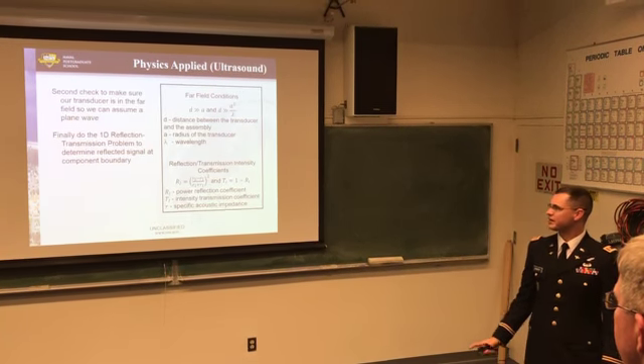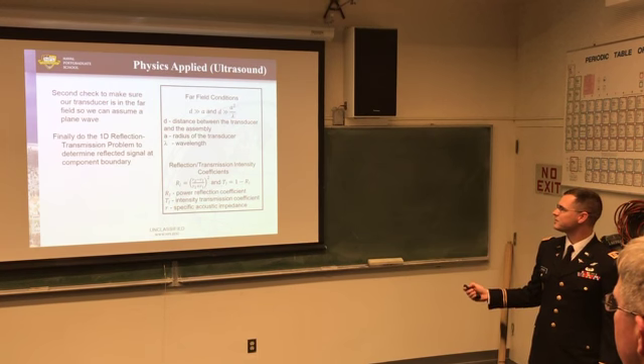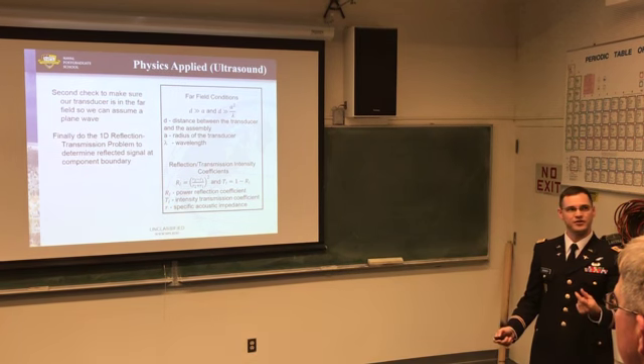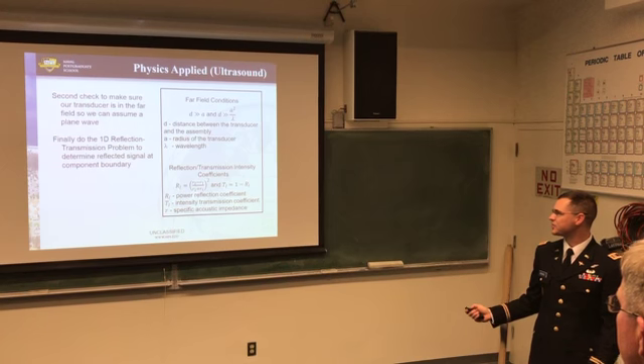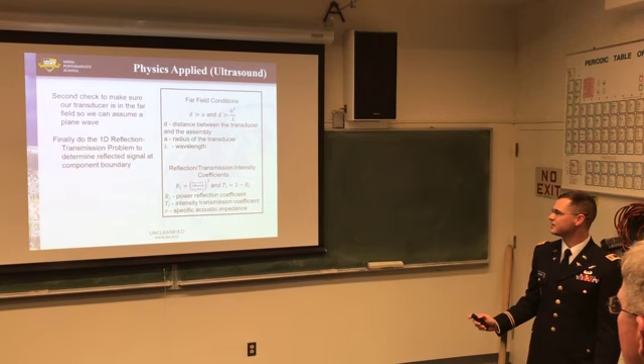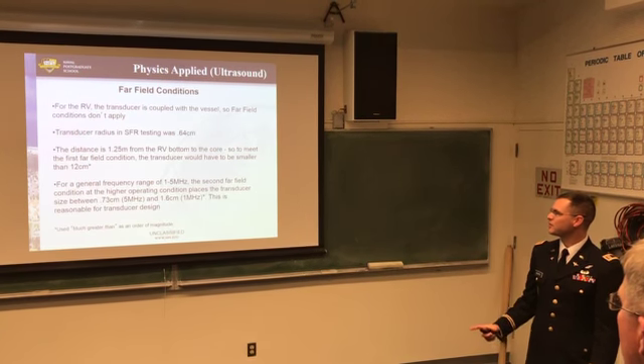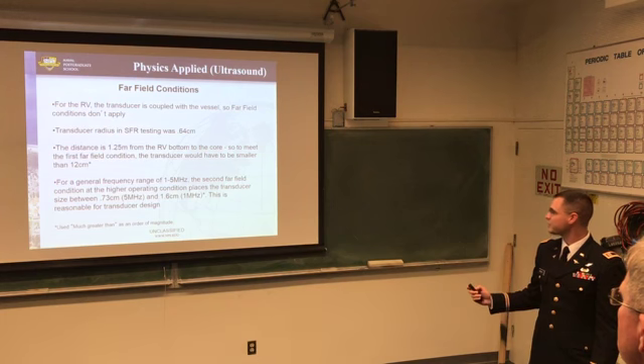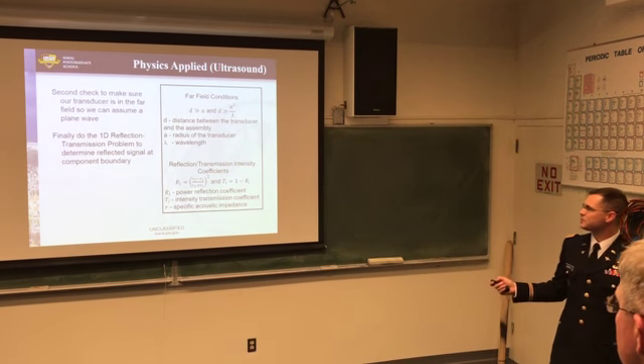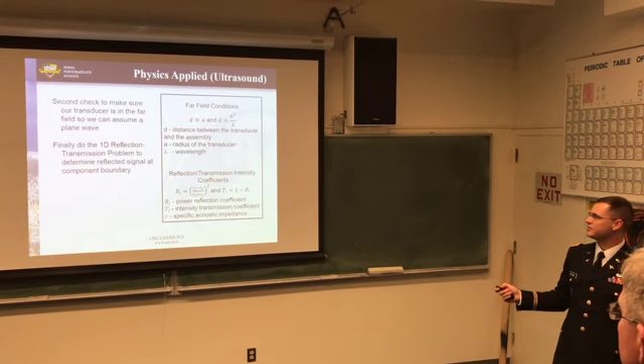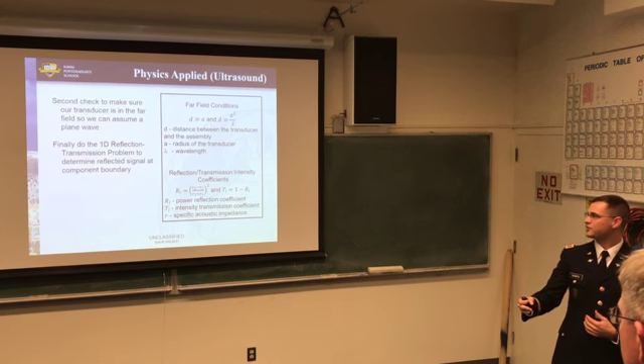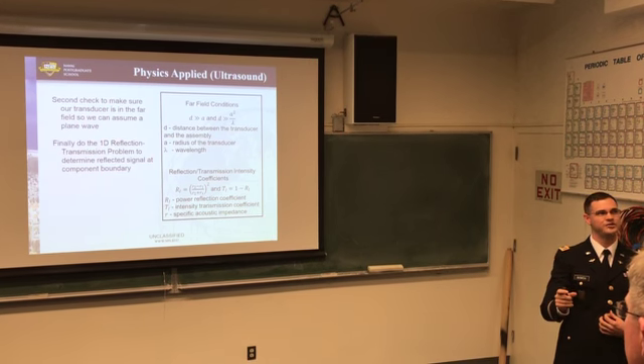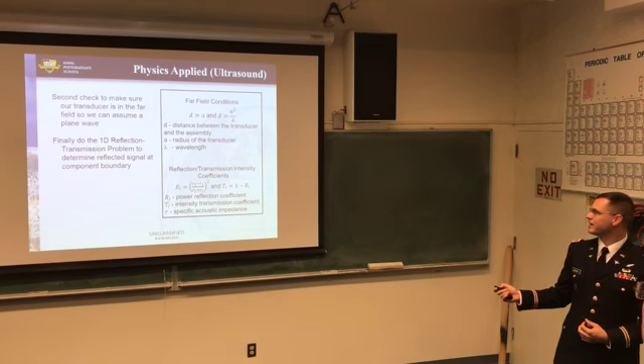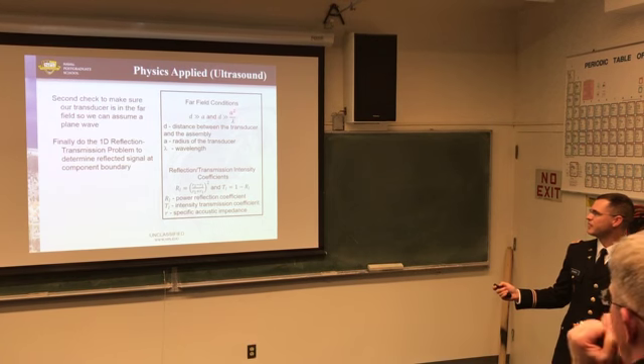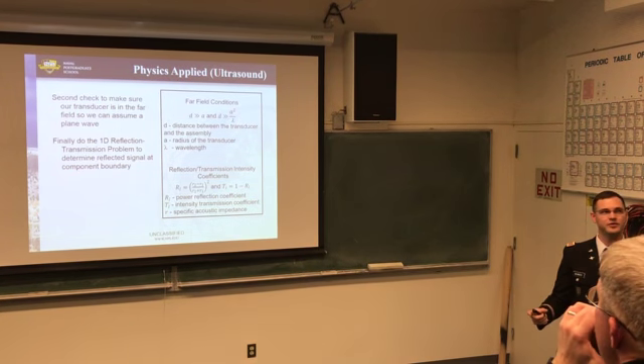So the next things we had to do were check far field conditions to make sure that our transducers would work, and check the reflection and transmission intensity. So for the far field condition, the conditions we used: the distance that you're traveling is much greater than a, which is the radius of the transducer, and then the radius squared over the wavelength, the two far field conditions.